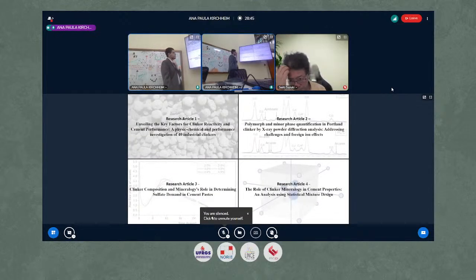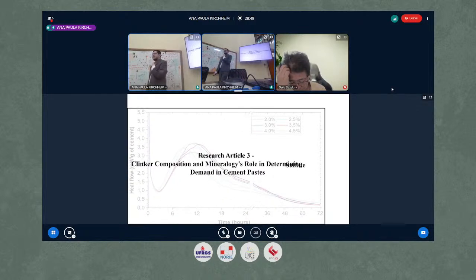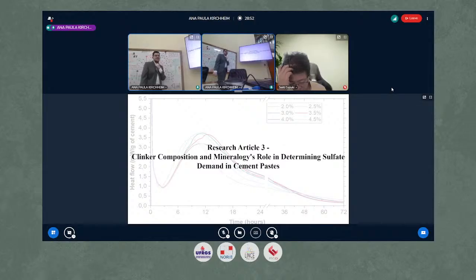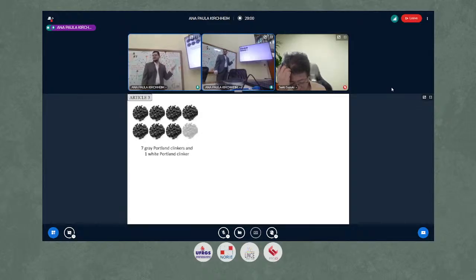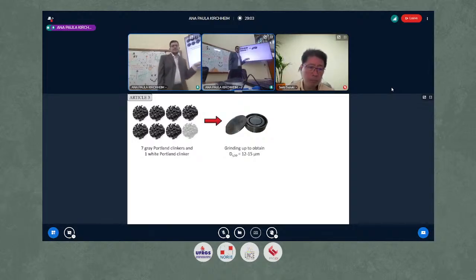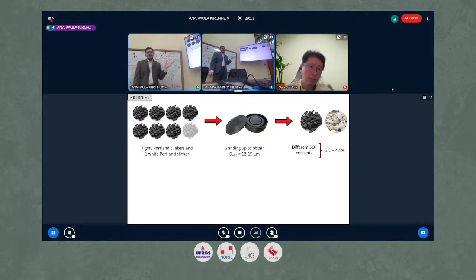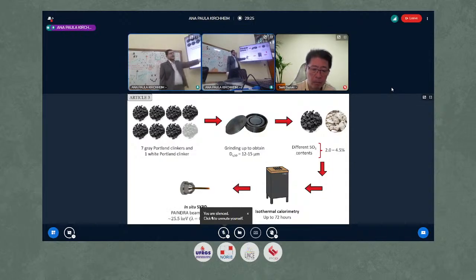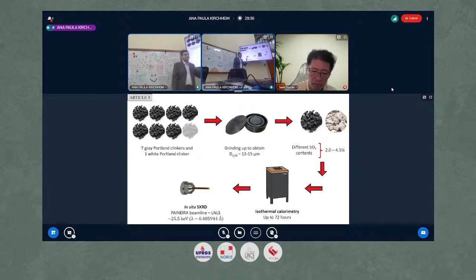So going to the third study, here we evaluated the clinker composition and mineralogy role in determining sulfate demand in cement pastes. Here we use the same clinkers from the previous study. We ground them, as I said, to obtain similar particle size distributions. So we vary the type. And here we optimize sulfate, varying the gypsum, varying the sulfate content, and optimize the sulfate with isothermal calorimetry. We then analyze the phase assemblage in the first 24 hours by in situ XRD, and here we run only the optimal mixes, optimized mixes, but also two others that I will show